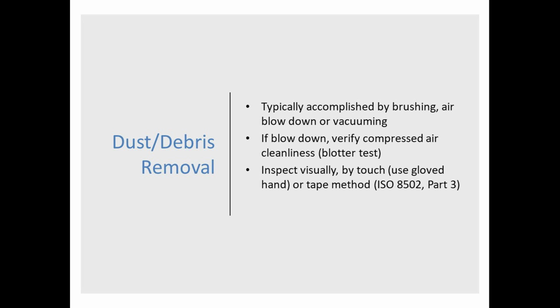That can be inspected either visually by swiping a gloved hand across the surface and seeing if you see a mark on the steel, or we can use an ISO method. Now the ISO method can only be used if it's in the specification, because the specification is going to have to give you an acceptance criterion, 1, 2, 3, 4, or 5. But basically you take a clear piece of tape, put it on the blast clean steel after the dust has been removed by brush off, blow down, or whatever, and then ultimately after you put that piece of tape on the surface, transfer it over to a piece of white paper or white backing of some type, and rate the quantity of dust you see on there. So if your specification said dust quantity rating of 3 or less, you know what's acceptable.